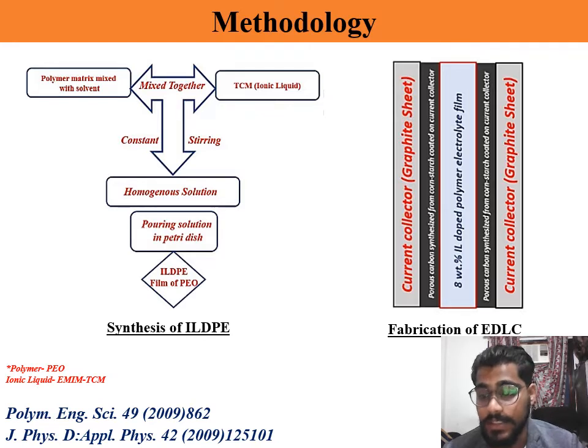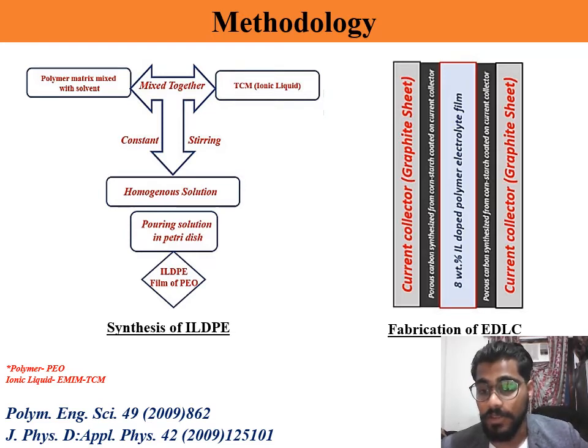They were synthesized using the solution cast technique. Firstly, 500 mg of the polymer, PEO, was used, and it was stirred in methanol solvent at around 400 to 500 rpm overnight. The next day, we observed a very clear homogeneous solution.